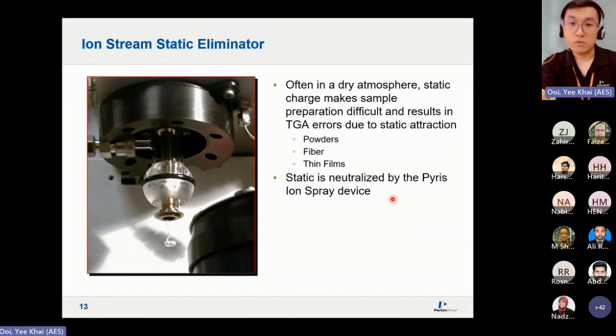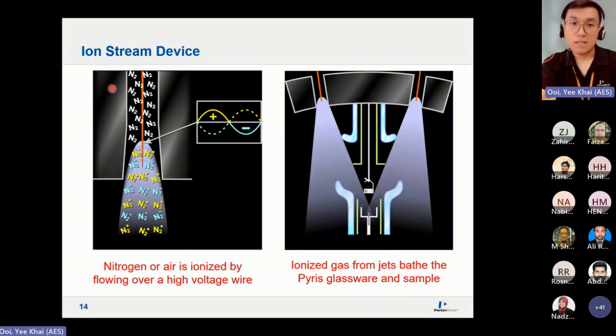For those running a lot of powder samples, fiber samples, thin film samples, when you are running this type of solid materials, it usually generates lots of static. The static will cause the pan to stick to the side of the furnace, causing a weight reading error. So when the glassware is being raised up, we have ion stream static eliminators to remove all the static generated. How it works is, the nitrogen gas coming from, whether you are using a tank or generator, will pass through a high voltage wire and become ionized nitrogen gas.